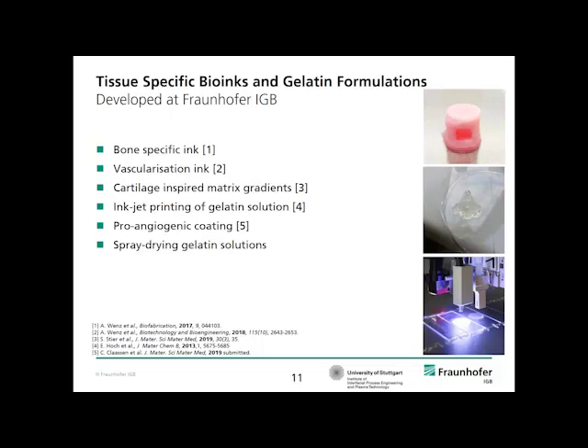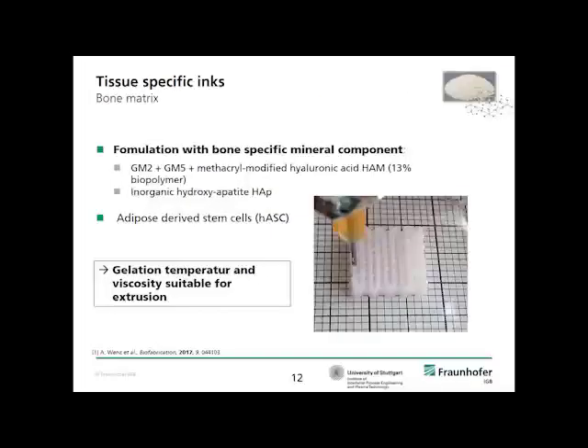We used our materials also for pro-angiogenic coatings, and we can show that spray drying becomes easier or possible with higher concentrations when we use modified gelatins. The first example is an ink that was formulated with a view to reproduction of bone tissue, and this means that we have a gelatin-based hydrogel ink, which also contains a mineral component,